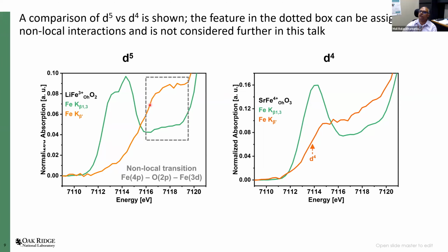I should also point out that there is an extra feature here at slightly higher energies. This feature is typically attributed to a non-local transition, which involves the iron 4p at the absorbing atom interacting with a further away metal. In this case, I've just shown it as an iron 3D coupled through this exchange coupling through this oxygen 2p. We will not, in this talk, consider this interaction further, other than noting that this feature is present in most of the compounds that we have studied.